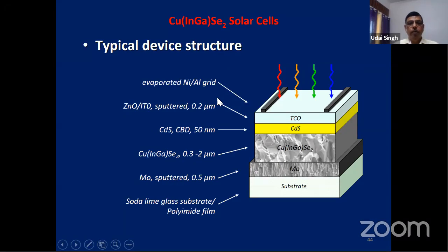So if you are going to make a typical device, you have a substrate, which can be soda lime glass or polyimide. On that, you have to coat a back contact, because for the PN junction you have to take a contact on both sides. One is referred to as the back contact, the other is the front contact. Molybdenum is used, which one can deposit by sputtering. Then you have a p-type copper indium gallium selenide, which is also referred to as the absorber layer because it absorbs most of the light. Then you have an n-type material, which is commonly cadmium sulfide.